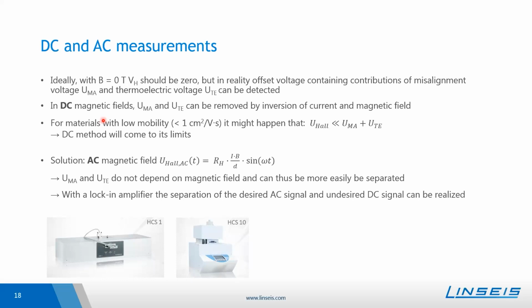In DC magnetic fields, typically by just inverting the current and the magnetic field direction, you can remove those two contributions. But for materials which have a very low mobility, below about 1 centimeter squared per volt second, it might happen that the signal of the Hall voltage is significantly lower than the sum of the misalignment voltage and the thermoelectric voltage. So by the inversion of the current and the magnetic field direction, and by subtracting that from the measured signal, only a very, very low value will remain. And this is very hard to resolve with good accuracy, so in this case, the DC method will just come to its limits.